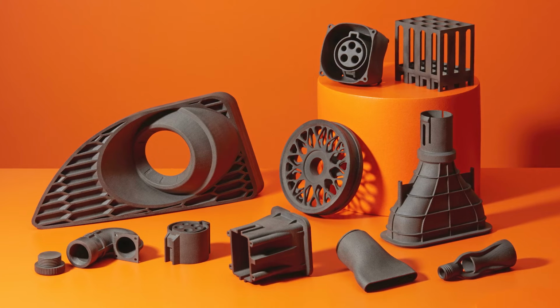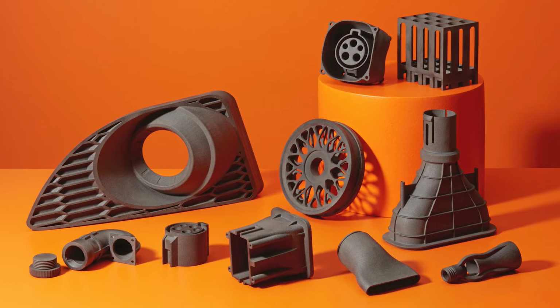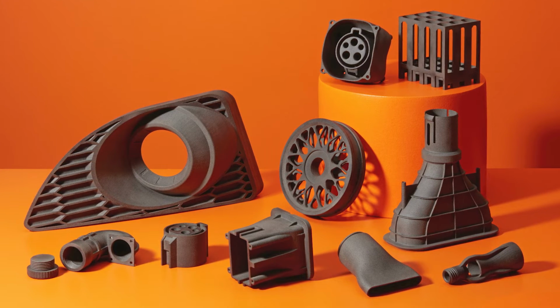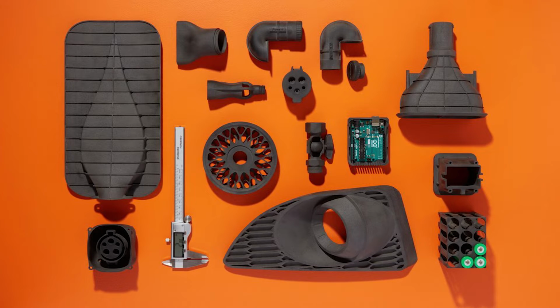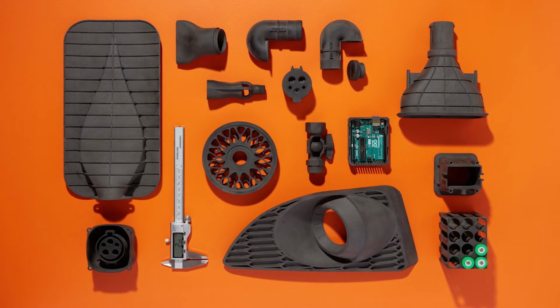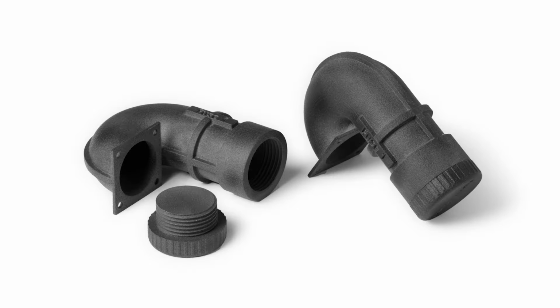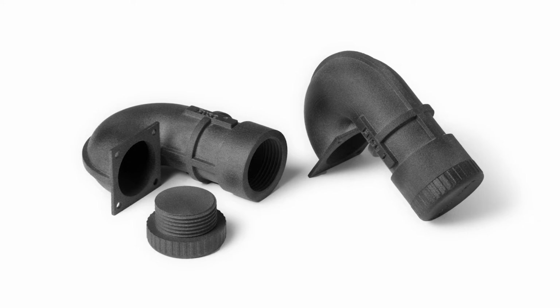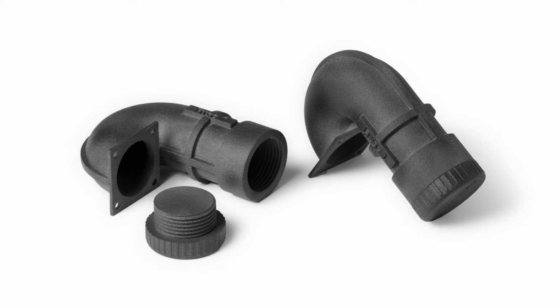GF stands for glass filled, and you guessed it, it has glass in it. With the glass, it has a higher tensile modulus, so essentially stiffer and therefore used in high accuracy applications. On top of that, with the glass inside, it makes it more chemically resistant, so there are customers using it for parts that are exposed to solvents in factories.